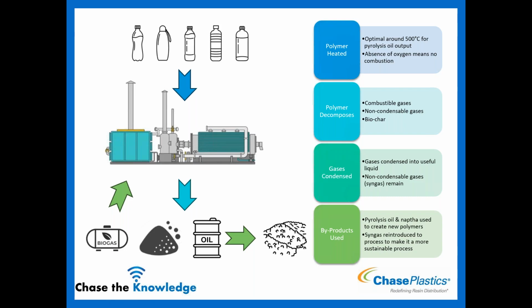And then we condense the gases. So the ones that can be condensed down do get condensed down into useful liquids. That's what gives you your pyrolysis oil. And then the non-condensable gases, your syngas remains, that actually then is used. So the byproducts are being used now. The gas can be put back into the system. So it's actually a fairly efficient system. It's a little more sustainable by itself because some of the byproducts get put back in to keep it running.